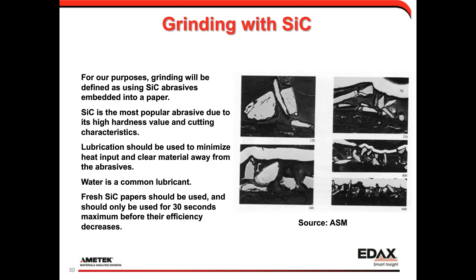Really, one of the most important things is that these silicon carbide papers have a finite lifetime. They're called consumables for a reason. And so we only use them for 30 seconds each before we call them finished. Then we'll switch to a new paper. And that's something we learned and we found to be very effective, is that by replacing and using a new paper, we get more efficient polishing. We actually get better results in less time.